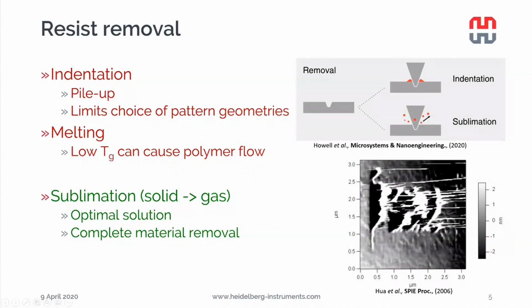Another issue that we have to consider is the melting and thermal properties. If you have a low glass transition point, basically a glass transition that happens before the decomposition, you can get a liquid state and start to smear the polymer across the surface, as we can see in this pattern where we wrote from left to right. And we can see these liquid strands of polymer that get smeared across the surface.